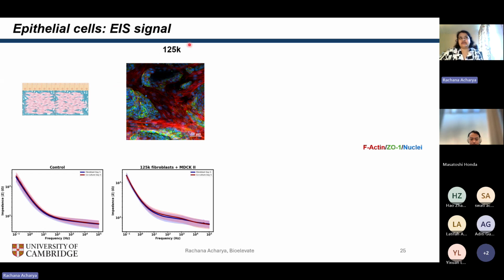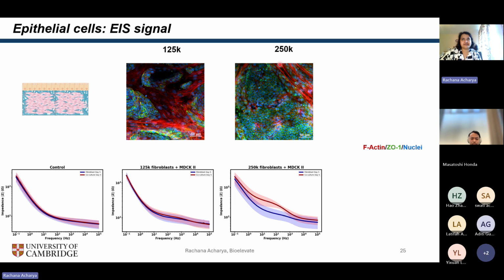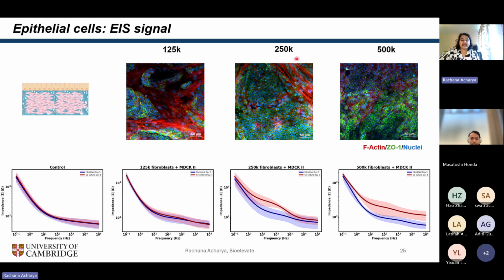For the low density fibroblast cells, which was 125,000 fibroblasts, I see that there is a slight increase in the impedance, or a slight barrier signal, on the 5th day of the co-culture, or 10 days of total culture, but not really much of a change, or not really much of a barrier formation. Whereas for the 250,000 and 500,000, so for the medium and high densities, I see this large change in the mid frequency impedance. And as you can imagine from these images, that's because these cells are now able to form a nice complete monolayer, which is giving rise to this barrier formation.